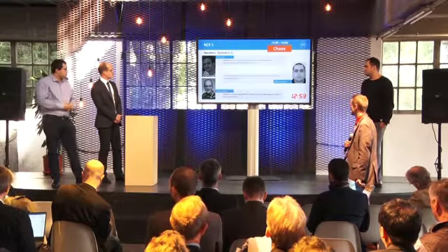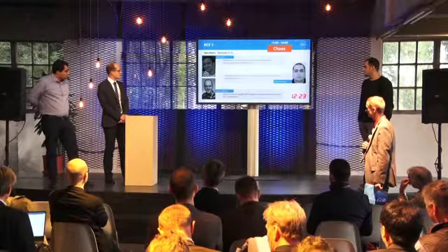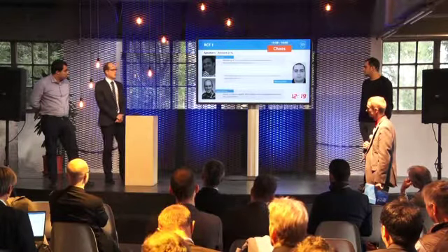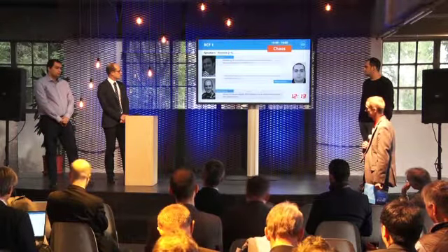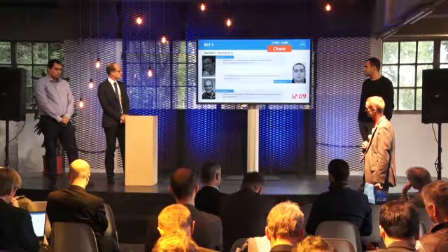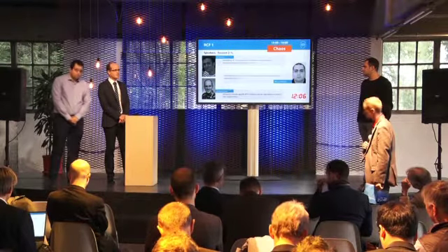It allows us to transfer specific RCF-relevant railway operating conditions into experiments. I hope I could show you that it's important that we have developed a methodology to identify those loading conditions in operation that contribute large increments of damage in a simulation, at least to crack initiation, and how to define or specify appropriate test rig experiments based on this data.